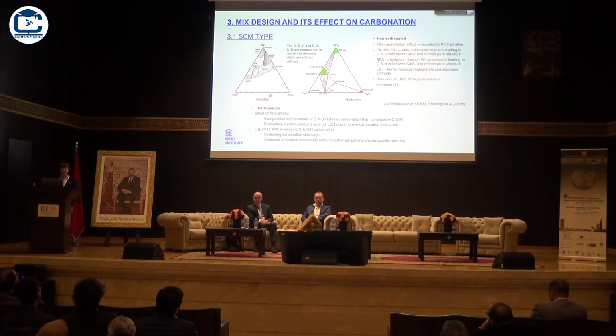Carbonation will also depend, of course, on the mix design, and we have already seen that in the ternary diagram. If you add different SCMs to the picture, they have a different oxide composition than the Portland clinker, and their reaction will also lead to other hydration products. So actually what's happening if you add supplementary cementitious materials is that you have, on the one hand, a filler effect and a dilution effect. So in the first stages you have an increase of the clinker reaction because you have deposition of your reaction products on your clinker grains, and also dilution, you have more water, so you have more acceleration of